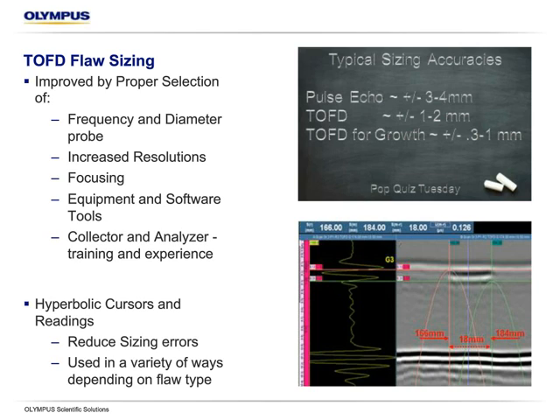Typically with TOFD, we use hyperbolic cursors to measure the length and the height of the flaw. We can see in the bottom picture here, those are positioned using the different colors first, and then going to the actual A-scan at certain points to be able to measure the width and the height extents very accurately. This will reduce some sizing errors. The reason we use a hyperbolic cursor is basically to undo some of those effects of beam spread. There are algorithms worked in based on the thickness of the component and some other factors, and by fitting them to the natural shape of the flaw, we can get a better length and height measurement, which helps us make the right call.